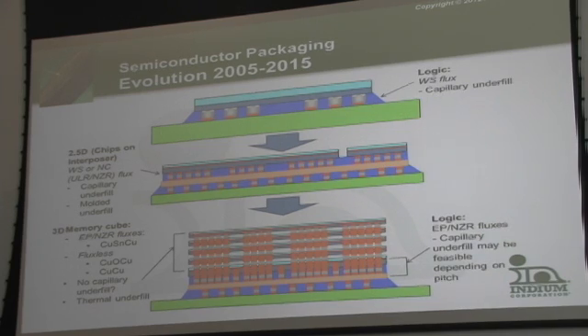In order to get around these problems, and these problems again only get worse as the node gets smaller and smaller, we've now moved to a copper pillar type approach. Rather than having just solder on the surface of the wafer, you now have a copper pillar, which is a true pillar of copper plated onto the surface of the wafer at each of these IOs, these interconnects here, usually with a little blob of solder plated on the tip of it. And this is then placed on a thing called an interposer.